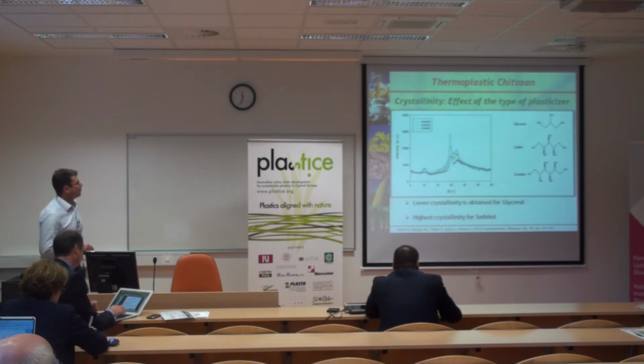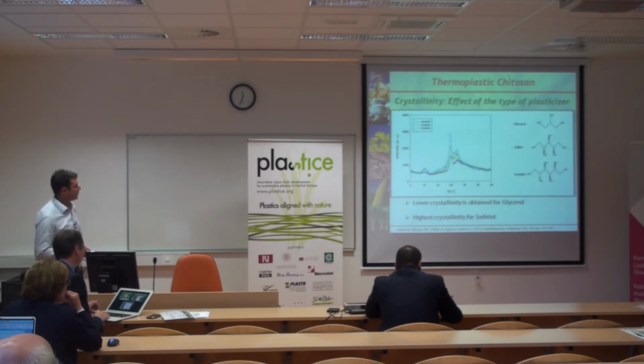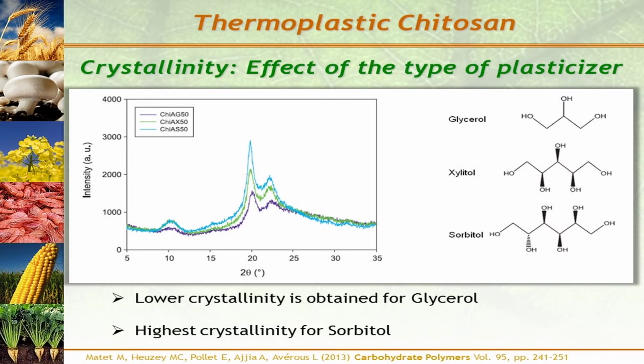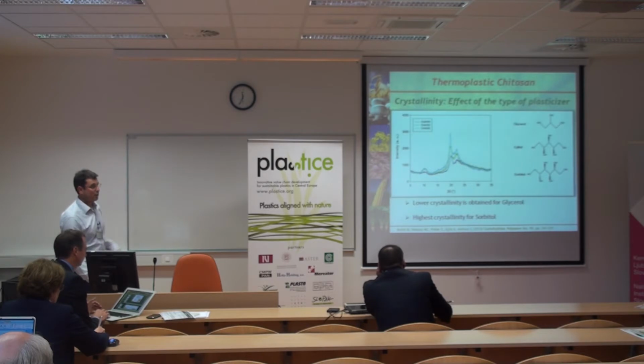I've shown you before material properties with glycerol as a plasticizer, but we have also studied other polyols like xylitol and sorbitol, and these tend to give higher crystallinity material, and the lowest one being obtained for glycerol. This was not surprising because we have more or less similar behavior with plasticized starch and sorbitol, for instance, which can crystallize during the post-processing aging of the material, inducing this crystallization of the plasticized chitosan.